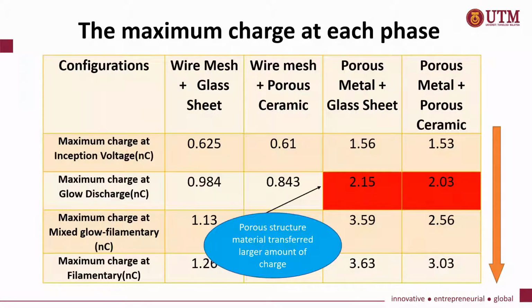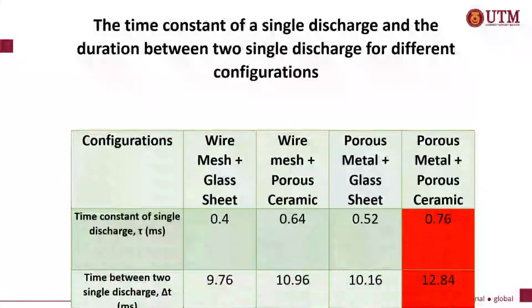On combining the results tabulated in Table 1 and Table 2, we can see that as the value of the maximum charge transported between the electrodes increases, the lower the applied voltage required to obtain the glow discharge plasma. The time constant for a single discharge and the duration between two consecutive single discharges for each configuration at the glow discharge phase were measured from the current waveform and recorded in this table.